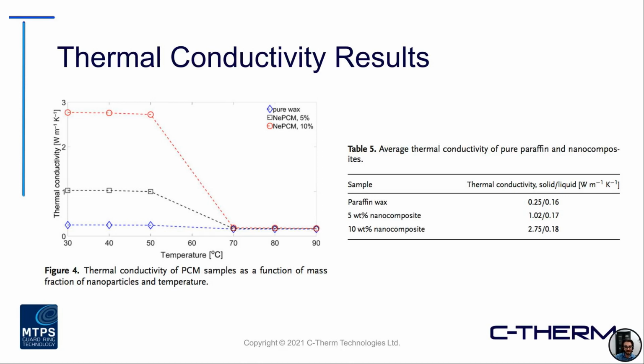You do notice that as you also analyze this data as a function of temperature, in its solid phase, we're getting a very distinguishable difference, but important to note that when you do approach that liquid phase, that transition of phase here, you do start to see some, I'll call them diminishing returns at the upper end. And again, this is simply related to, you can imagine a solid material has really good conduction pathways. As it becomes more of a liquid state, the disorganization of that matrix has a quite notable effect on the effective thermal conductivity.